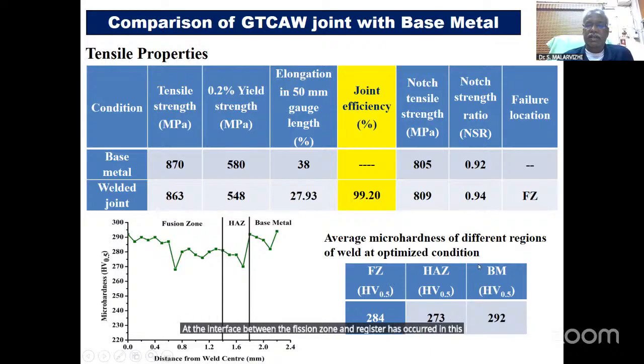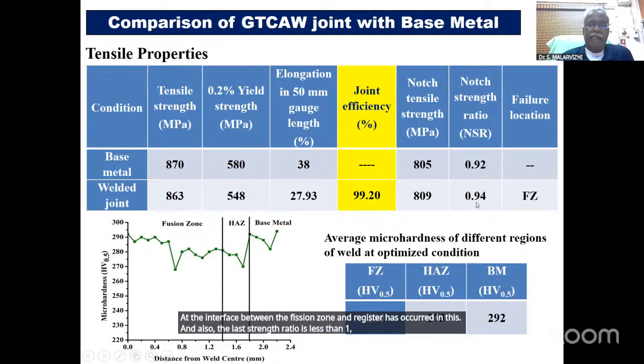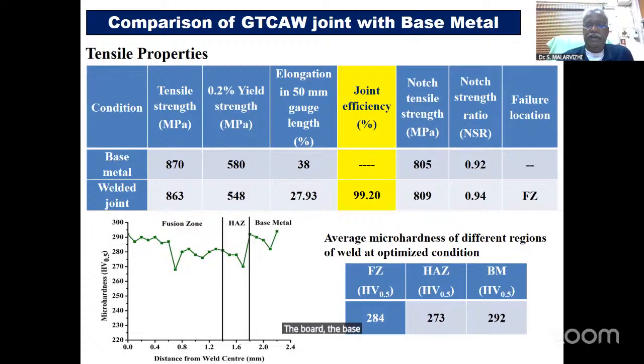And also the notch strength ratio is less than 1. That indicates that both the base metal and the welded joint are notch brittle materials. If you introduce a notch, it will behave like a brittle material.